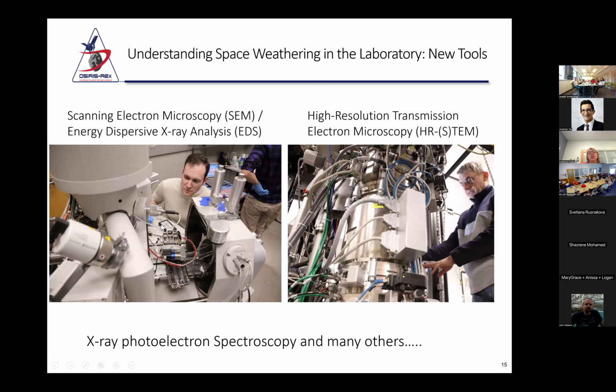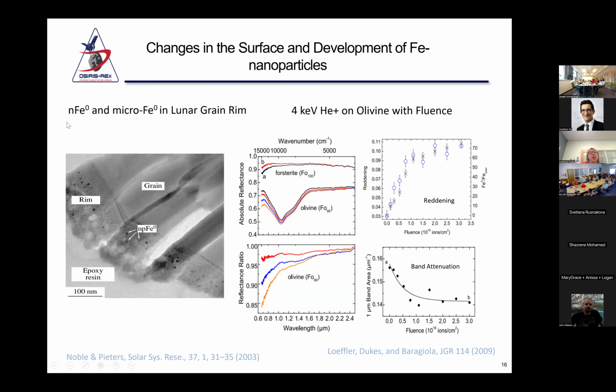It wasn't until we developed more sophisticated instrumentation in the 70s and 80s that we were able to really understand what was happening. It turns out that in the lunar case, with ion impact and also meteoritic impact, there is the formation of these little iron nanoparticles that darken and attenuate the surface. You can see this with other methods. This is an optical method. You see the same thing with ion fluence, and you see a change in the reddening of the surface as you form these iron nanoparticles.